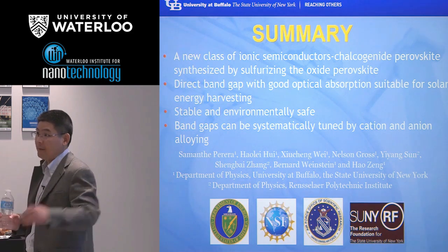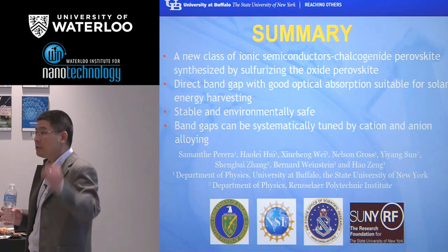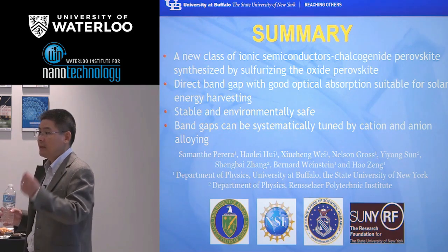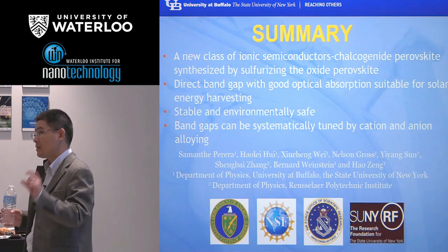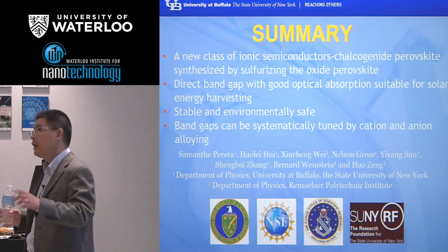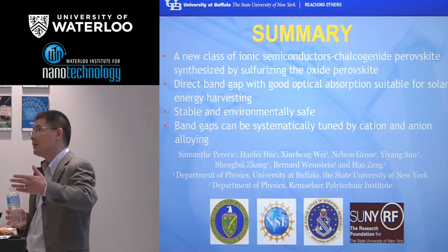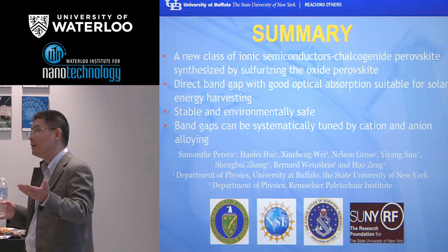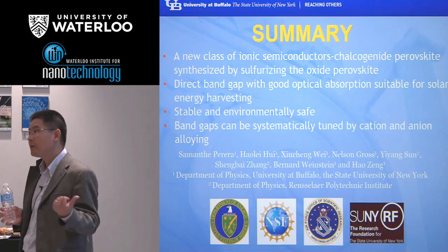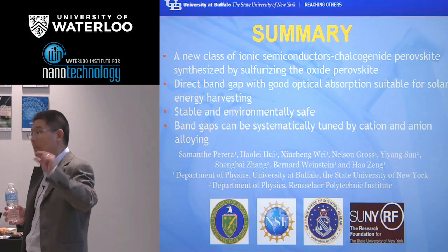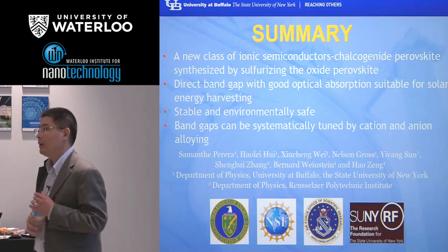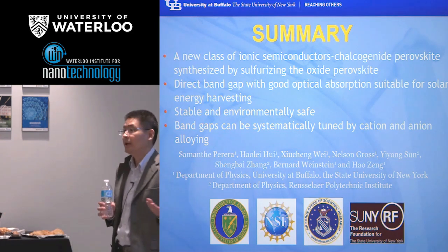The hope is that this thin film material is going to be more cost-effective than silicon, right? Because silicon is an indirect bandgap material, which means it does not absorb light very efficiently. Then you have to use very thick material, right? By thick, I mean 180 micron. Now, if you use this thin film material, you can go down to 1 micron. So you save a lot of material, in terms of material cost, right?